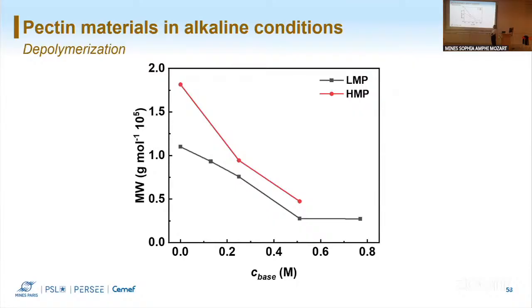So what happens then when you keep increasing the base concentration? The water prefers to be with the metal ions, and it goes away from pectin, to say it simply, and then pectin stays alone in the corner. Exactly, roughly what you described. By adding more base, you basically create a solvent that cannot accommodate polymer anymore, so it is more prone to exclude polymer. Yes. And that's what you very clearly see with sodium hydroxide. But with potassium hydroxide, you don't really see that, or you still see a salting out effect, but you don't see that high effect on the strength of your gel.